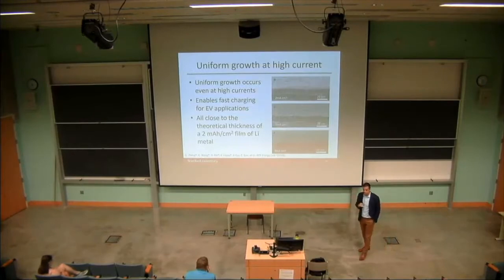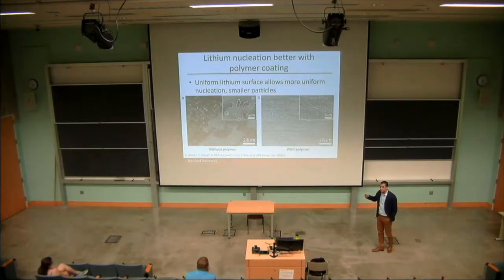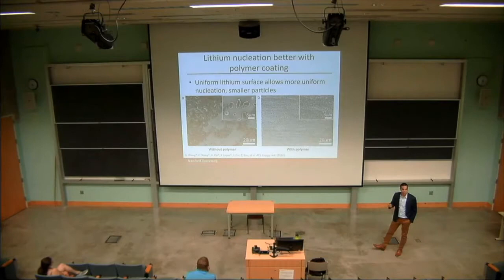When we were thinking about why exactly we were getting such dense lithium growth, we turned to the nucleation to understand that. So this is 10% of the lithium that we deposited before, just 0.1 milliamp hour. And then we take it out and we look at the SEM. You can see here, this is copper and then the lithium nuclei or particles that have formed on the copper surface, and they're very sparsely distributed. You see these large patches of copper that are left bare.